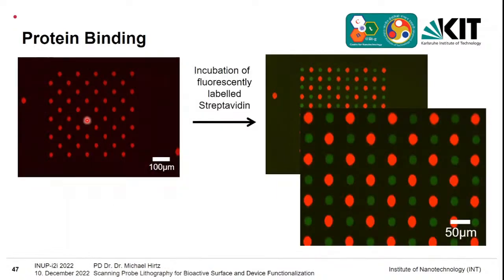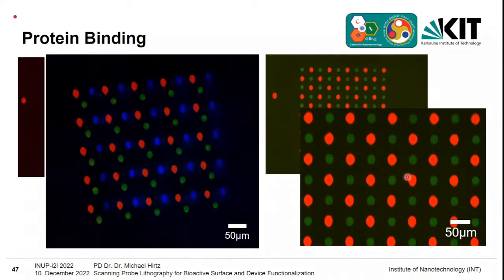So if we then go on and incubate labeled streptavidin, then all of a sudden the drops in between also light up. This is again because now we have the biotinylated molecules here on the surface, and the streptavidin binds to it, and then you can see again the full array. And of course we can also do that again multiplex. So here it's also like with a protein spot and 2 different fluorophores, as before.